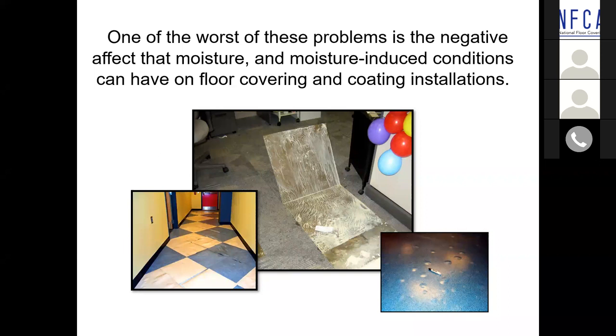When is it reemulsification? Well, it's more often reemulsification if the adhesive never achieved its necessary degree of set in a wet set sheet vinyl, sheet rubber, sheet linoleum installation, where the surface of the concrete is still dense and not permeable, such that the free water in the adhesive is not being readily absorbed into the surface of the concrete. What happens is everything looks great. You put the floor down, you roll it, everything looks great till they start trafficking the floor.